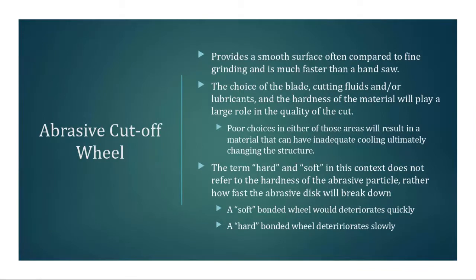If you're using too little or lack of cutting fluids and lubricants, you overheat the sample, and then what ends up happening is you end up with very large burrs, material smearing, and that will alter your microstructure. And then once again, the hardness of the material is going to play a role. So once again, if it's a hard material and you're using the wrong blade, that ends up being an issue. So you need to make sure that the choices between those 3 or 4 combinations are going to give you the optimal sectioning method so you can just move right into metallography.